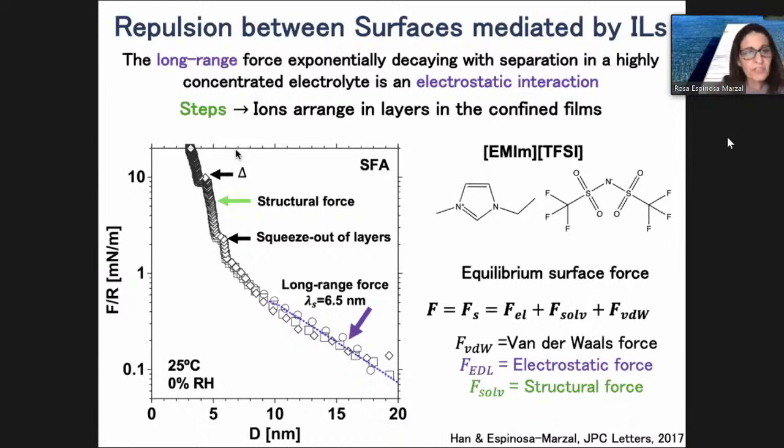I will focus on the shorter range force, which is what we call a solvation or a structural force, and as you can see, there are some steps embedded in the force profile. These steps reflect that the ions are organized in layers, and every time we squeeze out one of these layers, we measure a step. And from the thickness of these steps, we can determine the thickness of the layers of ions.